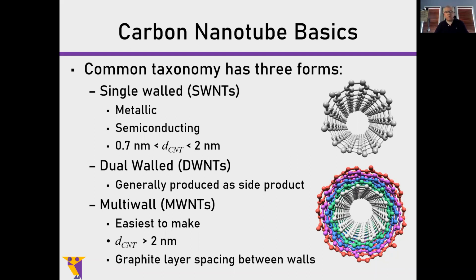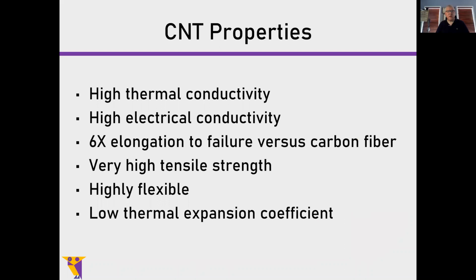Dual walls are just that. They have 2 walls. Most industrial production is not centered on dual walls. They do occur, but they occur as a side product. Most production is multi-wall nanotubes. These are the easiest to make. They typically have diameters greater than 2 nanometers. And between the walls, you've got a standard graphite spacing of about 0.34 nanometers. So it's really easy to count these things and figure out how many walls you have.